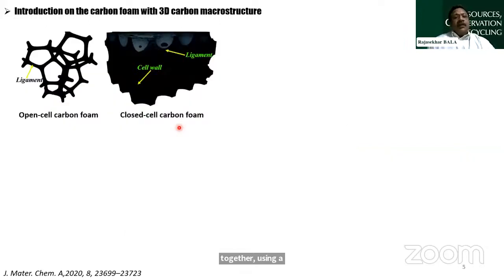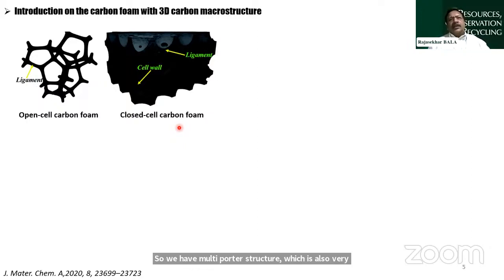Having said that, when it comes to carbon foam, which is nothing but the 3D macromolecular structure, it can exist in two different forms. It could be an open cell carbon foam, or it could be a closed cell carbon foam. What we are looking for is more like a closed cell carbon foam, because that has a high level of porosity. So we have a multi-porous structure, which is also very rigid. In other words, it will have high mechanical strength as well. So that's the kind of carbon foam that we were targeting initially as part of our research, and I will tell you how we achieved our target through the synthesis work.